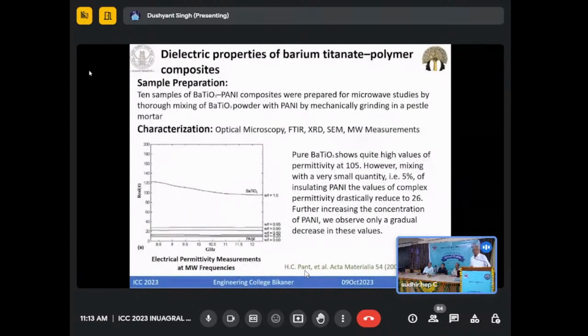If you take pure barium titanate, its dielectric constant is 100 plus. But if you add about 5% of polyaniline base, this dielectric constant drastically comes down to around 25. Now it is not explained by any law of mixing. When you mix two materials, they should follow the law of mixing. That means they should gradually come down. But it is coming down very rapidly with very small concentration.